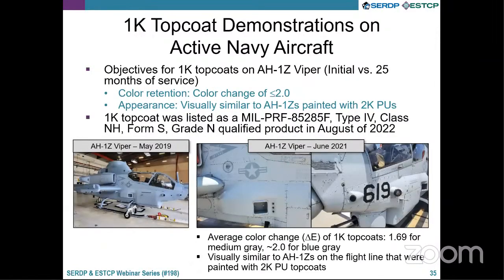This was one of 6 aircraft painted during a year and a half span. We monitored each aircraft every 6 months, taking color, DFT, and gloss measurements and photographs, and observing for delamination, cracking, or hydrocarbon damage. After that 25-month period, the top coats had a color change of less than 2, which was our objective.